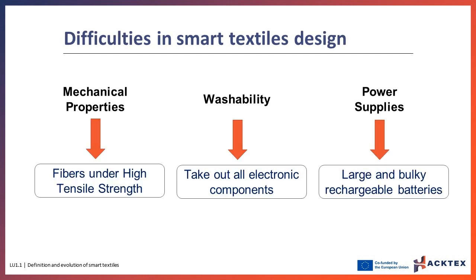Among the important challenges in smart textile creation is mechanical properties. If we compare to flexible display applications that are rolled around cylinders with diameters of a few centimeters, smart textile fibers are under high tensile stress and rolled in much smaller cylinders than one millimeter. The grade of tensile strain that e-fibers are under depends on the textile structure but also on the position of the body at which the textile circuit is placed. For example, textile fibers for shirts and jackets close to the upper neck receive high levels of pressure, and stress in a shirt can be up to 20% at the shoulder blades.